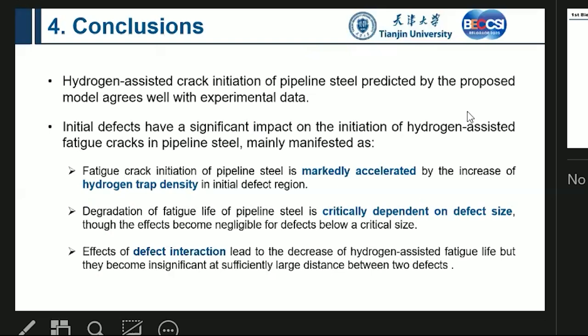And the second one is that the degradation of the fatigue life will critically depend on the defect size. So the effects can be negligible for defects below a critical size. Effects of defect interaction lead to a decrease of the hydrogen-assisted fatigue life, but they become insignificant at a sufficiently large distance between the two defects.